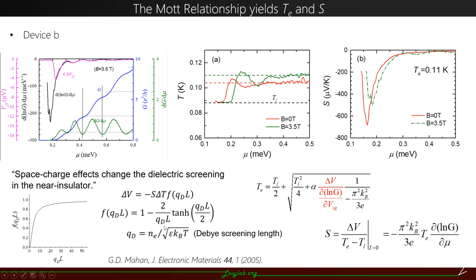He suggests that in the insulating state, the thermal voltage we measured should be corrected by a function, a dielectric screening function. This function approaches 0 when the electron density is 0. So when the quantum wire approaches the insulating state, we can measure 0 voltage. That does not necessarily mean that the Seebeck coefficient must also be 0. So in this case, we assume a constant electron temperature for the quantum wire, and we put it into the Seebeck coefficient. Then we can calculate the Seebeck coefficient.